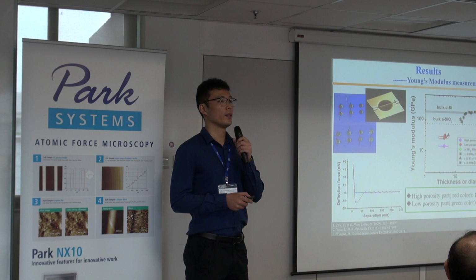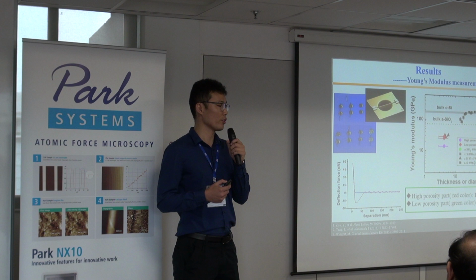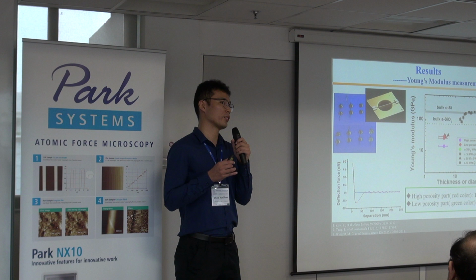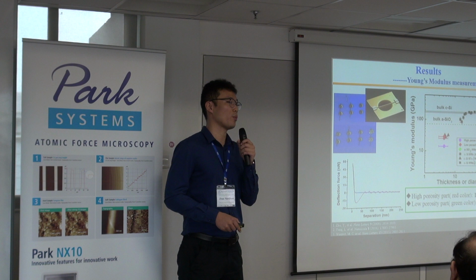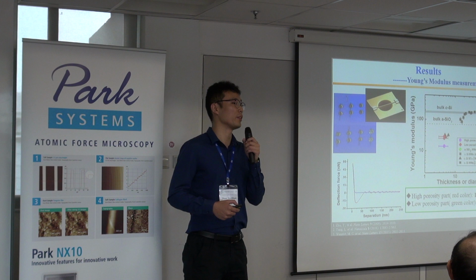Yes. Because in the nanoscale, from the calculation, the nanoscale has a higher surface to volume ratio, and also the surface atoms have free bonding. That's why the theoretical prediction is that the mechanical bonding is weak at the nanoscale. That's why we predict the nanoscale porous silicon has a lower Young's modulus compared with the bulk one. This value will be taken as the material value.